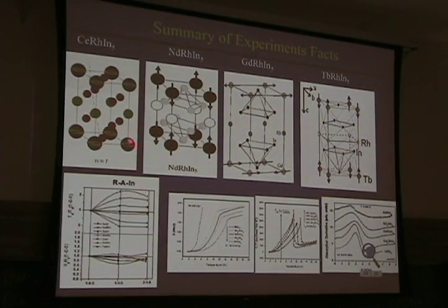Well, so we know the magnetic structure for cerium, neodymium, gadolinium, and terbium. Let's focus on the 115 now. The neodymium and terbium have the moment pointed along the c-axis, and the cerium one has the moment pointed in the plane. The magnetic moments are in the plane for CeRhIn5. So those compounds that order axially along the c-axis have T_N larger than the cubic. The compound that orders in the plane has a T_N lower for the tetragonal compound than the cubic.